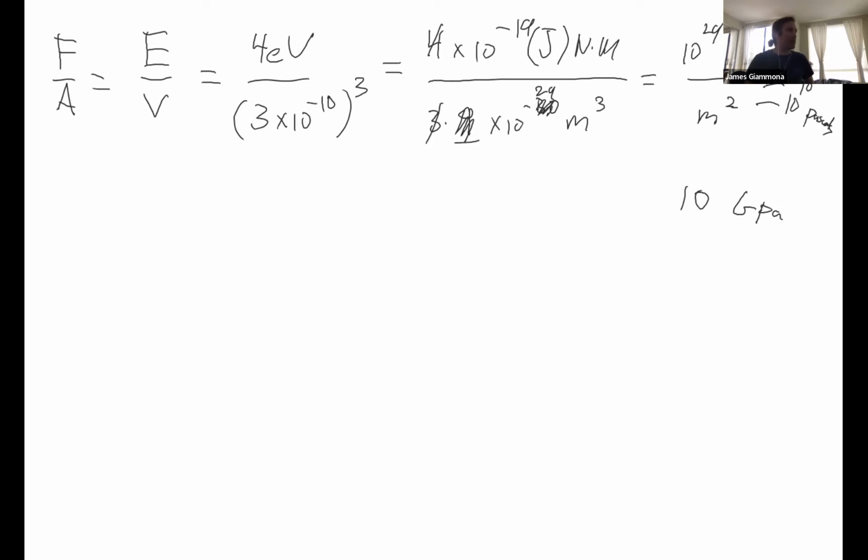And so this is interesting. This seems like high. So Venkat was saying in the chat that this seemed a little high, but actually it's about right. So steel varies between like 500 megapascal and like 2 gigapascal as its ultimate tensile strength. So we're actually in about the right ballpark.